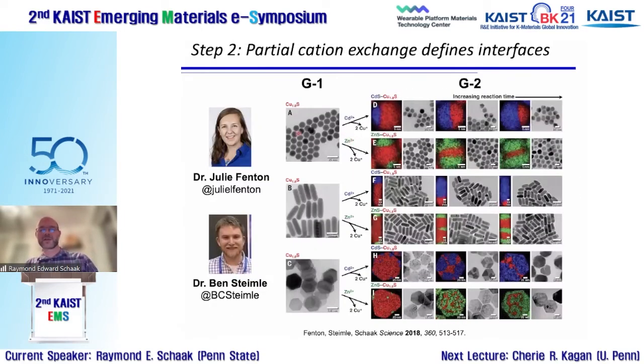And so for a zinc 2+ exchange on these copper sulfide spheres, indeed we see what Richard Robinson's group saw, that sandwich type structure emerge. But for cadmium, we see a progression that makes more of a Janus, a hemispherical particle. For the rods, for the cadmium, we see a one tip structure where you can almost see the front of the cation exchange growing as a function of reaction time. For zinc, we again get that sandwich type feature, although at increased time, we also get a central band growing in. So we have access to some unique structures here.